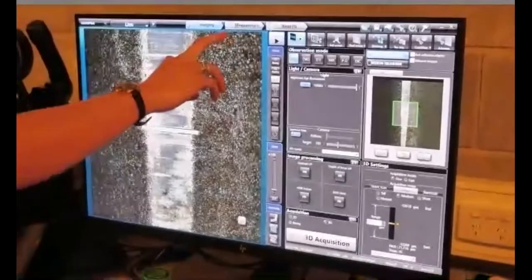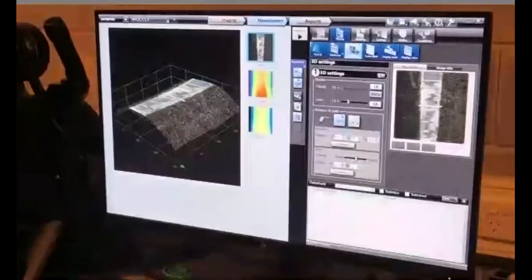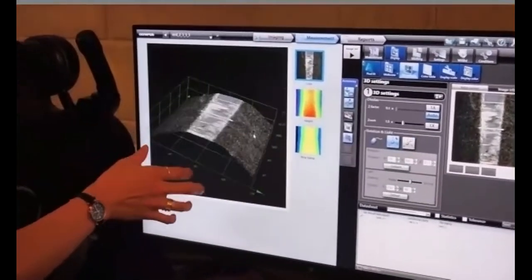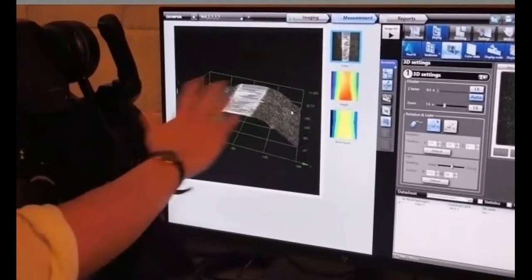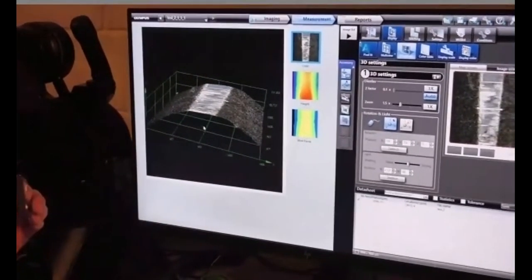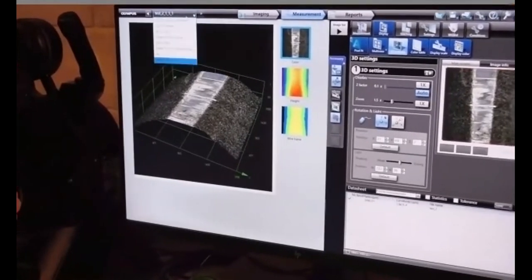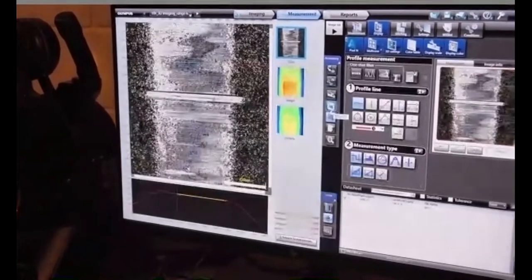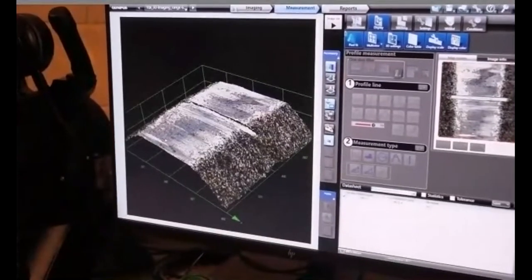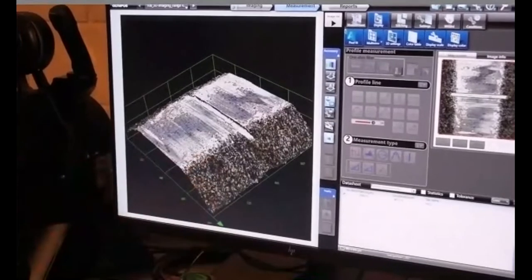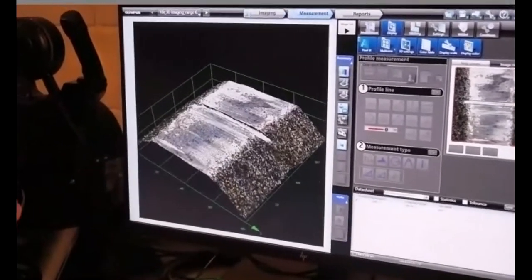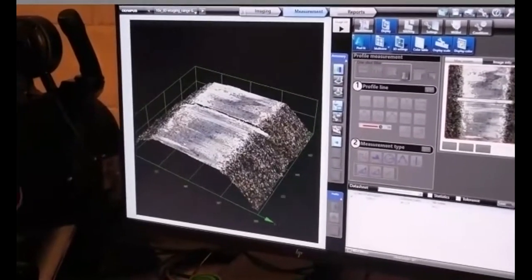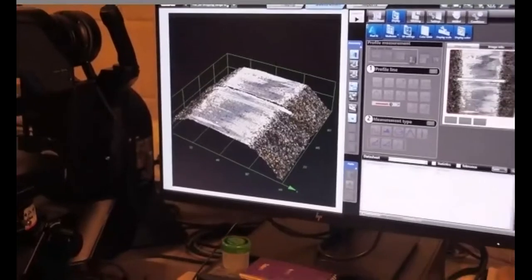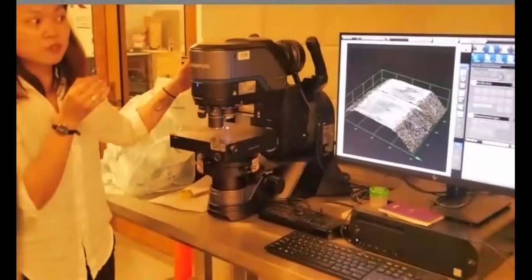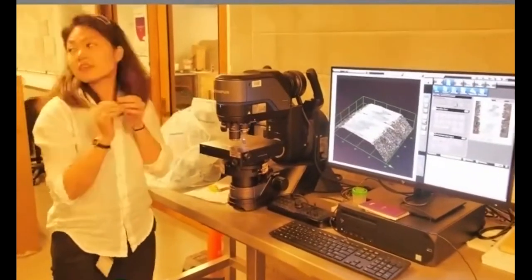So go to the measurements. This is the typical 3D image after we've taken that. Depending on the resolution of the lens, you can take a high resolution image where we're looking at, for example, a very deep wear mark on the top of the block. So we can examine that and then do a calculation on the wear profile. The other thing is this microscope frame can be rotated, which allows you to observe the sample surface at a different angle. So thank you.